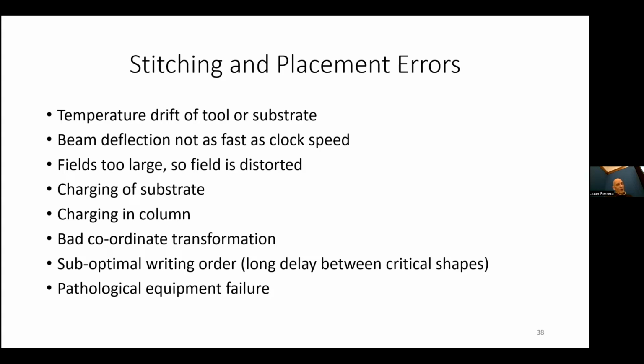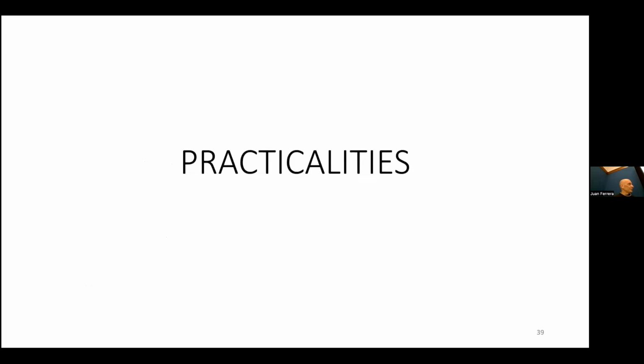In addition to bad coordinate transformation, if you don't really understand what you're doing when you do sample preparation, it's easy to get a coordinate transformation that leads to errors. And then if you're writing very small things or things that need to be connected across fields over long periods of time, some of these drift terms that aren't a problem when you're writing for half an hour will become a problem when you're writing for 8 hours. And of course, sometimes the equipment just screws up and you find out about it later.